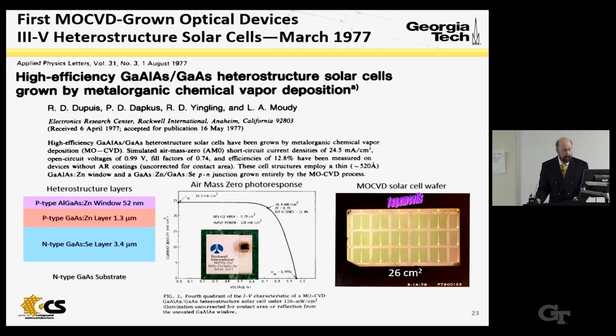solar simulator, simulating the spectrum in outer space, air mass zero, under one sun illumination. And on the right you see a solar cell wafer that I grew. Well, the picture says 79, so let's say early 79. It was the largest solar cell wafer produced at the time. It's the largest piece of gallium arsenide you could buy that was low dislocation density. This was horizontal Bridgman grown gallium arsenide. And you can see 1 square centimeter cells fabricated on this device.